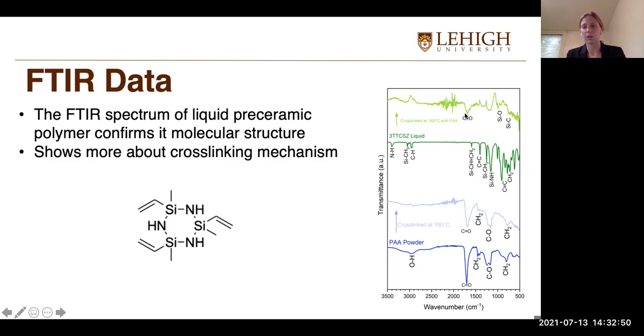So you can see that there's a decrease in the NH and SiCH3 peaks, which indicates that there was cross-linking via dehydrogenation or evolution of CH4 groups. And you can also see the SiCH double bonded to CH2, which indicates that the vinyl groups contributed to the polymerization. And finally, the appearance of the SiO peak suggests that there was ring opening where the nitrogen was replaced with oxygen during the cross-linking in air. So this really gave me some great information.